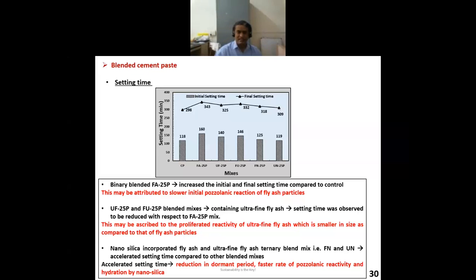But here you see how beautiful it is. It is similar to the control. That is my advantage. In a similar way, the final setting time also follows a similar trend. Basically, the binary blended fly ash mix is attributed to the slower initial pozzolanic reaction of fly ash particles. But the nanosilica combined with fly ash and ultrafine fly ash mix, that is FNUN, accelerated the setting time compared to other blended mixes.